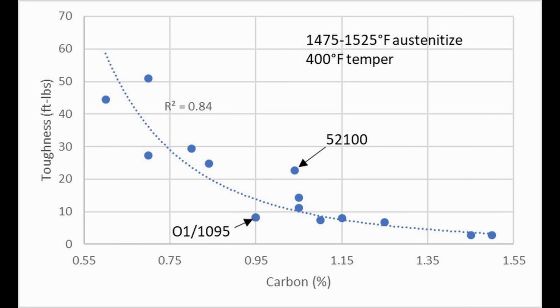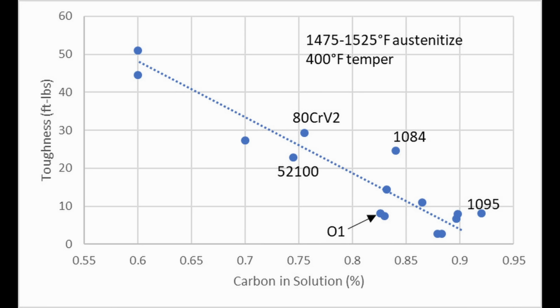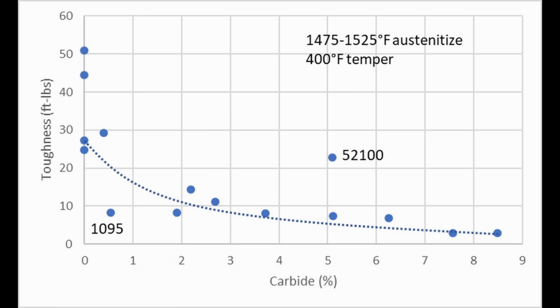So here is a plot of other low alloy steels versus carbon content, and as the carbon content goes up, the toughness goes down. One reason is that more carbon can be in solution, so the martensite itself is higher in carbon. That can lead to plate martensite and other factors that lead to lower toughness. The other thing is the high carbide content. So more carbon means higher carbide content. Carbides are brittle particles. The more of them you have, the less tough the steel is.